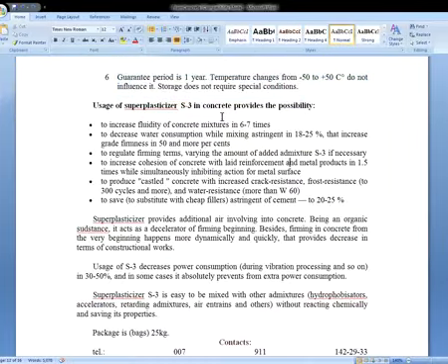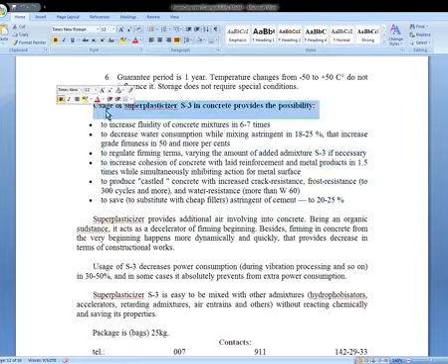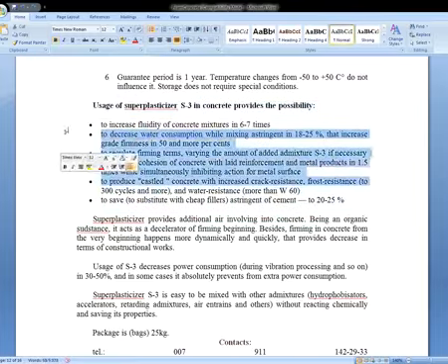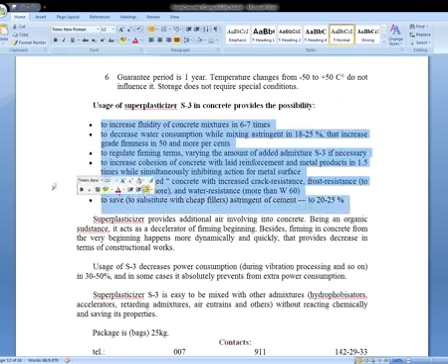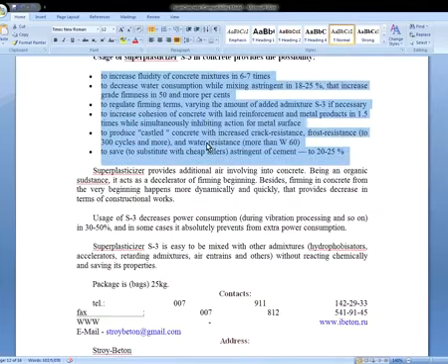So what are the uses of superplasticizer? This is superplasticizer. I call it plasticizer, it doesn't matter, it's the same thing. It is used to increase the fluidity of concrete mix, sometimes making it liquid enough to flow. To decrease water consumption while mixing by 18 to 25%, which increases grade firmness by 50 or more percent.